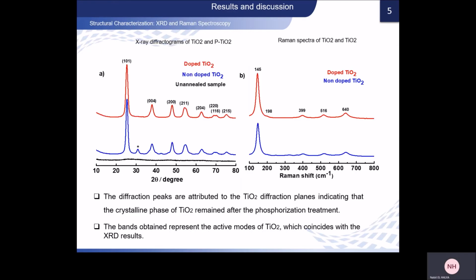The crystal structure of the doped and non-doped titanium dioxide were identified by XRD, as shown in this figure. These diffraction peaks, which are attributed to the diffraction planes of anatase titanium dioxide, indicate that the crystal phase of titanium dioxide remained after phosphorization treatment. The structure properties of the two materials were further examined by Raman spectroscopy. So these obtained bands represent the Raman active modes of anatase phase of titanium dioxide, which coincide with and confirm the XRD results.